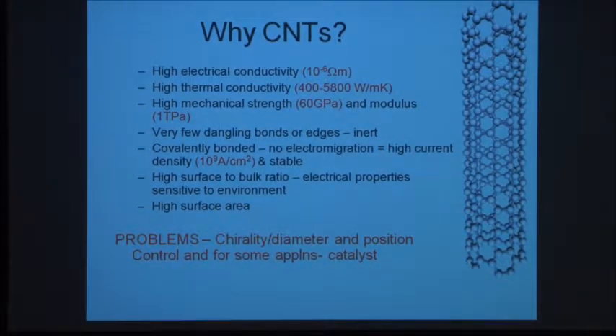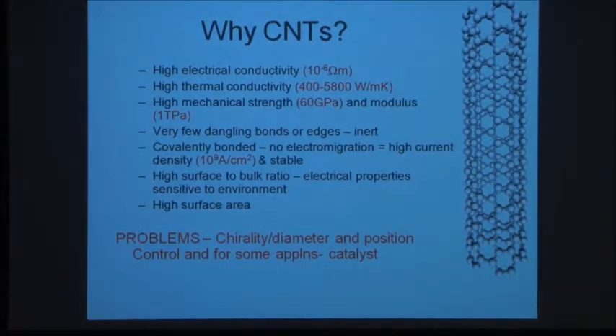So why were people so keen on CNTs? More or less the same reasons they're keen on graphene now. Very high conductivity, 10 to the minus 6. Very high thermal conductivity, so it can be used for thermal bonding, heat sinking. High mechanical strength. There have been lots of pretty pictures of nanotubes being used to tether satellites, etc. Very few dangling bonds, it's pretty inert. It's covalently bonded, which is very good if you want to drive very high currents through it. It leads to very, very low electromigration problems. A high surface to bulk ratio, as you can see, and so it's potentially very good for sensors. And that's the good stuff.